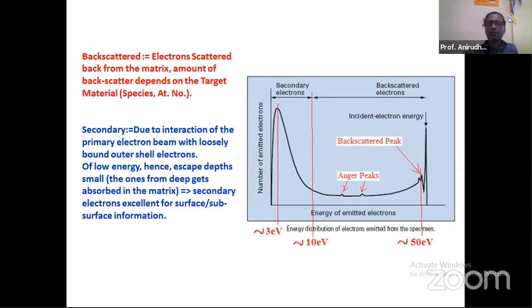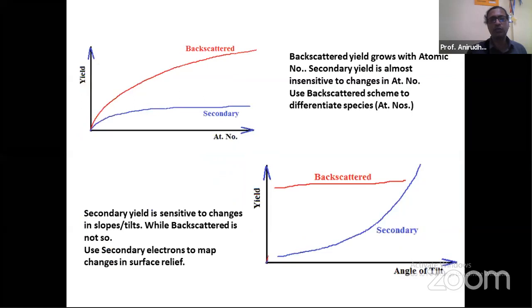They cannot be from deep inside, because if they were emerging from the depth, they would have got absorbed, as we discussed in the case of our XPS case. So therefore, since these secondary electrons should be from very low depths, they would carry useful information related to what is at the surface. And as surface scientists, as tribologists, we would find information from them to be very, very useful.